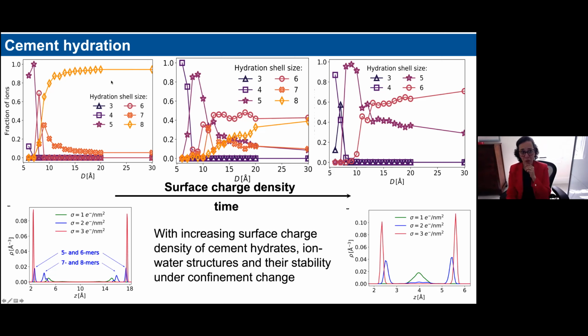So with this type of calculation, even if we have a very simple representation of the surfaces, represented basically just by their surface charge, and we use a relatively simple model for the water, we have a complete enough representation of how this phenomenon changes with the surface charge, with the degree of confinement, and with the type of ions, to understand not only why the material is cohesive and how cohesive it is at the end of the process, but also how interactions evolve over time as the surface charge density of the material changes.